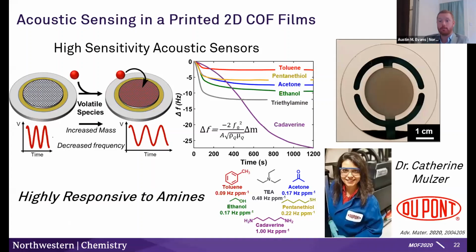Okay, so because we could deposit the material in a specific space, into a specific device geometry, what we decided to do was deposit the COF as an active material on a QCM wafer. And this is known as acoustic sensing, because essentially how it's going to work is that the active material is going to absorb some species. The resonant frequency of the quartz crystal microbalance underneath is going to change, and using the Sauerbrey equation, which I've shown in the graph on the right, we can extract the mass, or the amount of material that's been absorbed to the COF active layer.